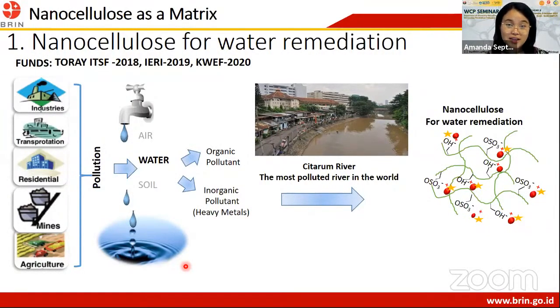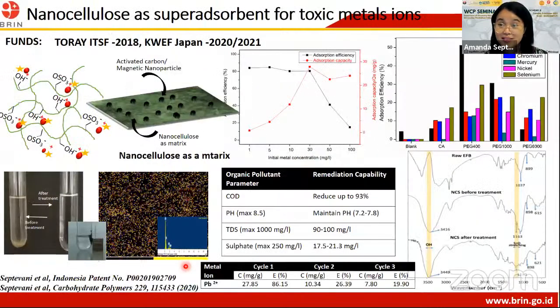So our nanocellulose has shown some promising results as a superadsorbent, in this case as a matrix. We already introduced two types of materials. First is the activated carbons, and second is the magnetic nanoparticles. In terms of the activated carbons, this nanocomposite already shows good promise, such as giving a really high efficiency to adsorb lead metals in contaminated waters. However, this cellulose composite is only selective to lead, while the other metals still have a low adsorption efficiency.